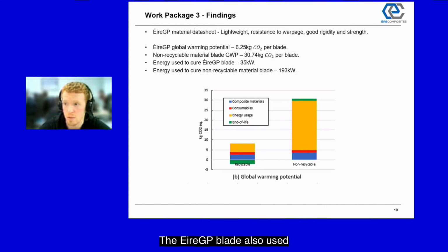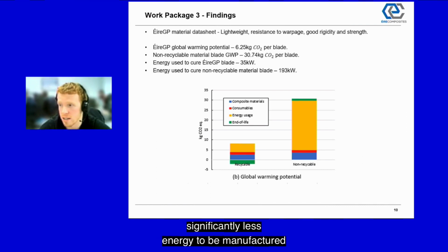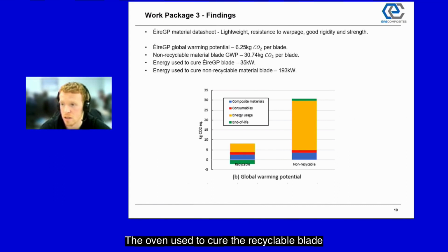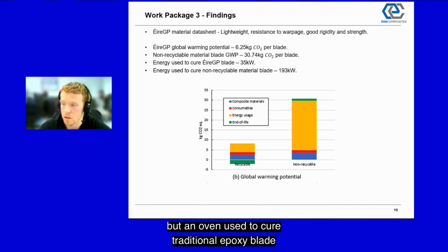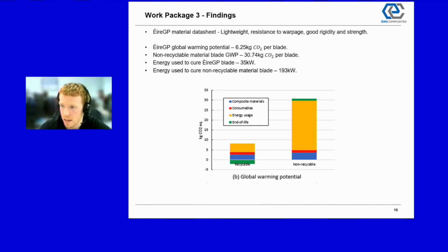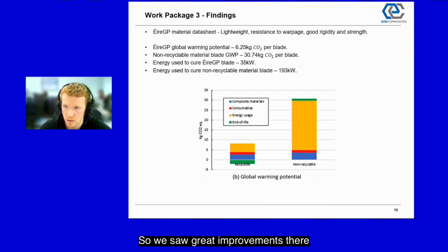The Eire GP blade also used significantly less energy to be manufactured than a traditional epoxy turbine blade. The oven used to cure the recyclable blade used 35 kilowatts of energy, while an oven used to cure a traditional epoxy blade would use approximately 193 kilowatts of energy. So we saw great improvements there for the recyclable material.